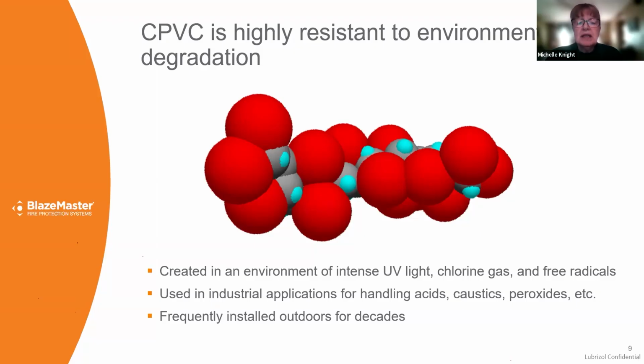So this gives it excellent resistance to free radicals created by UV light. It does not matter what the chlorine content of the water is, or if you need to shock chlorinate your system to kill microbes in it. You can't put enough chlorine in a fire sprinkler system to harm it. In fact, it's used in very high chlorine applications in the chlorine production industry in our Corzan products. And it's frequently installed outdoors, particularly plumbing and Corzan. And they're not being degraded by the UV light there.